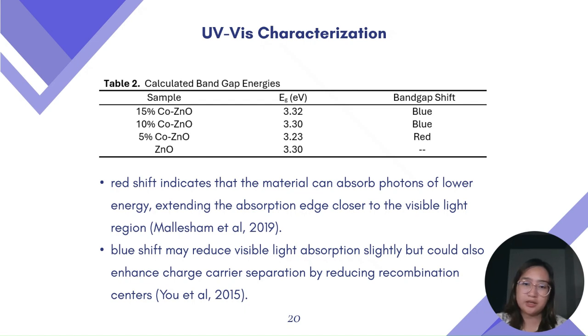A slight reduction in bandgap energy to 3.23 at 5% doping suggests a redshift, indicating that the material can absorb photons of lower energy, extending the absorption edge closer to the visible light region. It's beneficial for photocatalysts because it allows the catalyst to harness a larger portion of the solar spectrum, especially visible light, which constitutes the majority of sunlight.